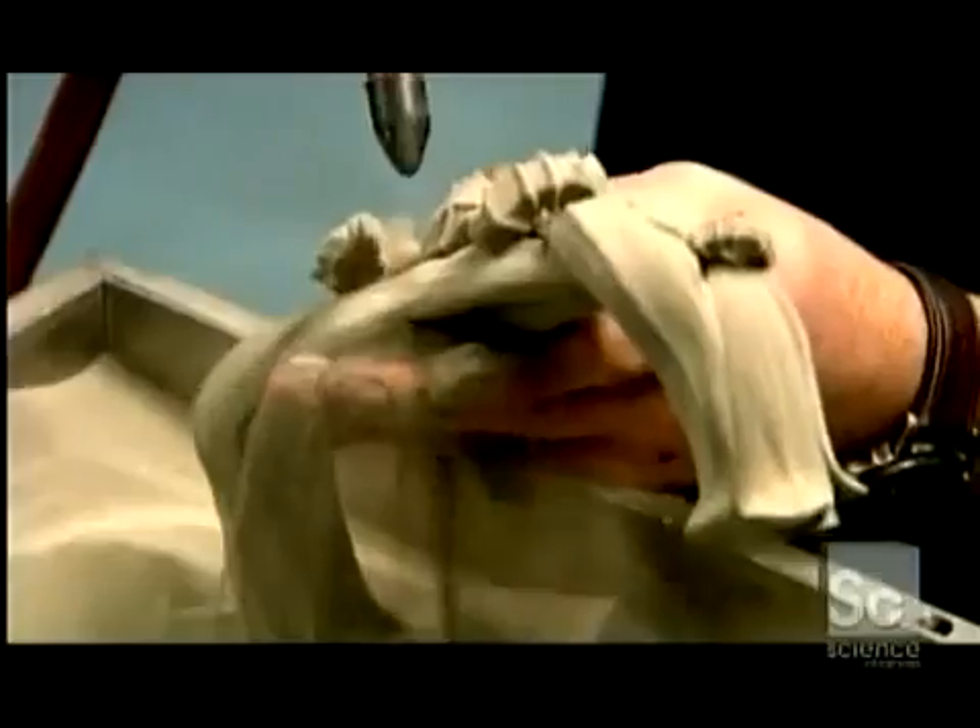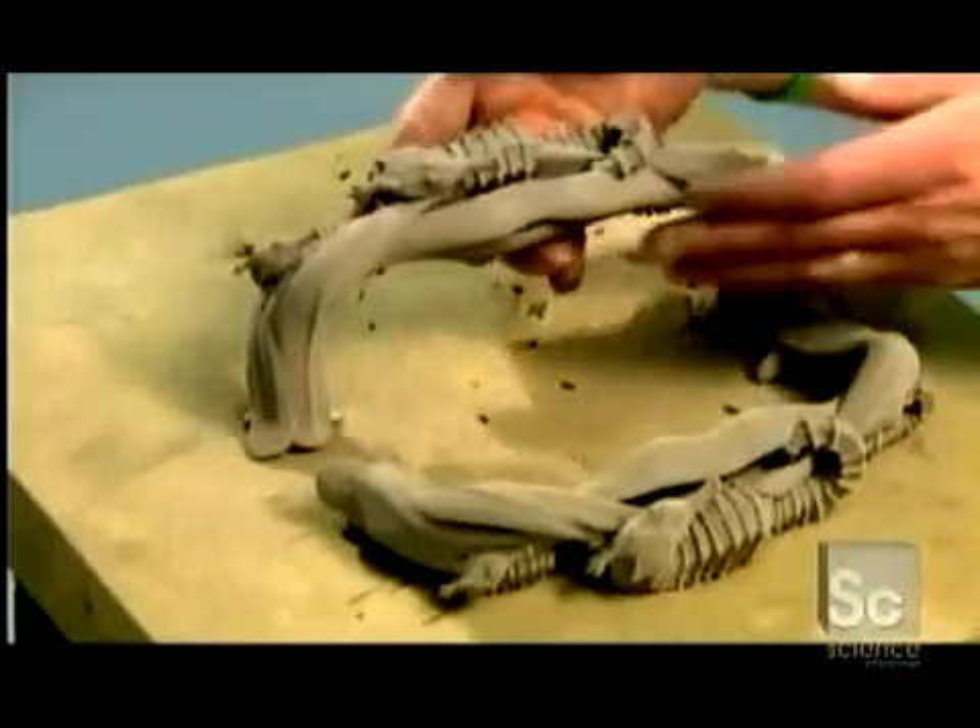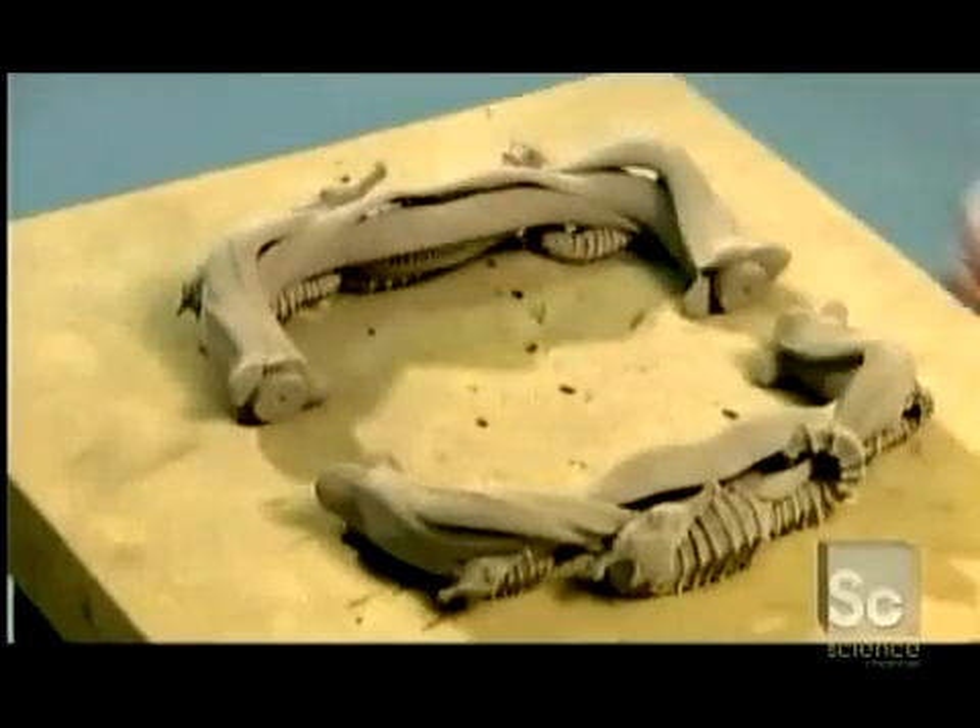At this point, the object is very porous and contains about 40% air. It is so fragile that it could easily be crushed with bare hands.